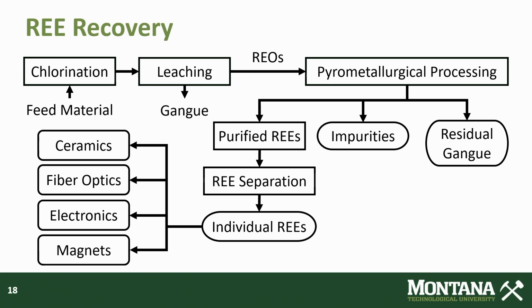However, we're going to have an appreciable iron content that's going to follow through, plus some residual materials that actually do make it into solution and are co-precipitated with the rare earth oxides. So when you see the residual gangue down on the bottom right, that's where we plan to reject that material as one of the pyrometallurgical steps.